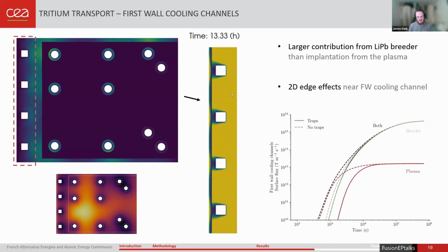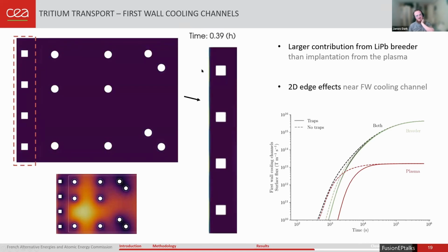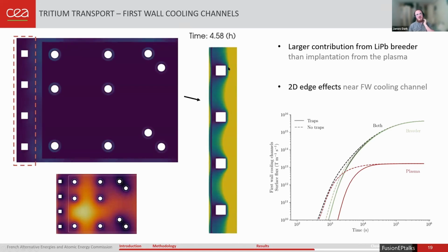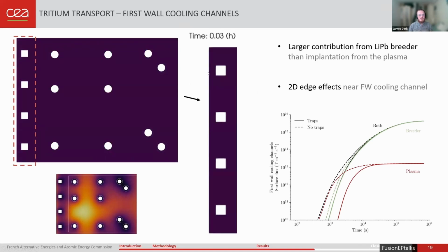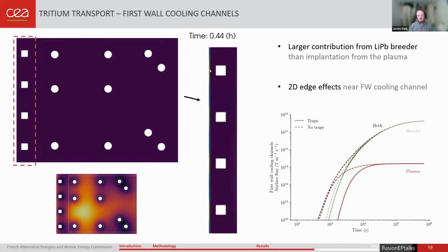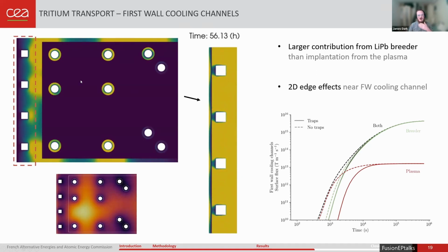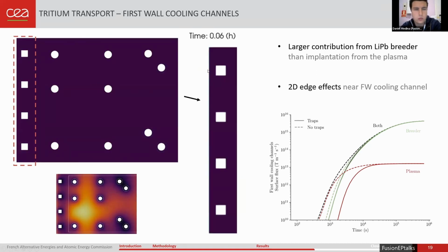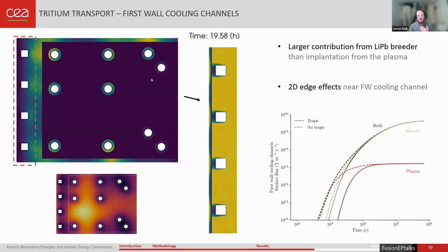Yeah, it's completely dominated. If you remember from the beginning, we have a kind of influx of 1e20 tritium per meter cube coming in from the plasma, and still, this is due to a few different things. One, the actual contribution is a bit lower, but also the trapping is so much more dominant in the tungsten as well, that there's still quite high concentration at the surface, but because so much of the population is being trapped, it's not necessarily all kind of free flowing.